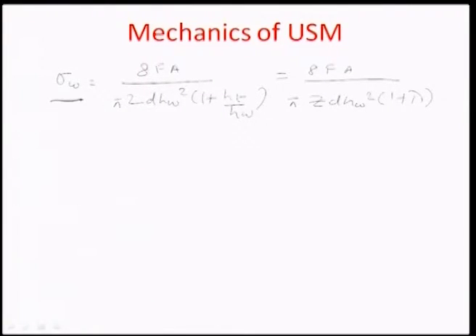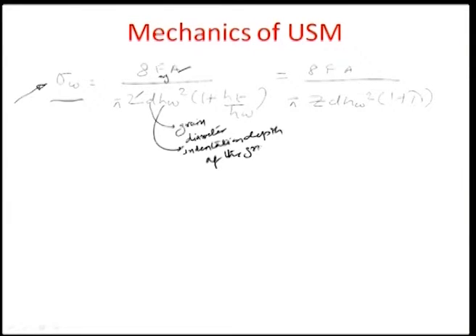And in the process of doing that, we arrived at a formulation given here in this slide, where we were talking about the ultimate yield stress of the workpiece, sigma W, and we correlated this to the average force that the vibrating tool head would give on the grains, the amplitude of motion of the tool A, and the number of grains or particles making impact per cycle. D right here was the grain diameter of the abrasive grains. HW was the indentation depth of the grain on the workpiece,